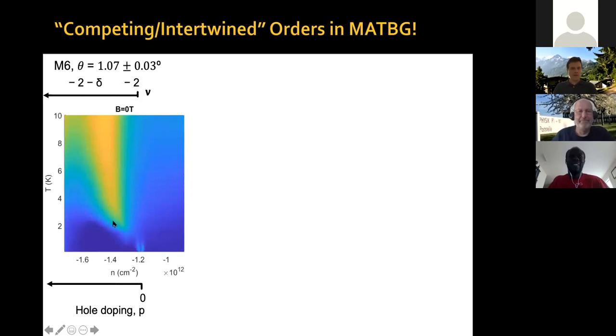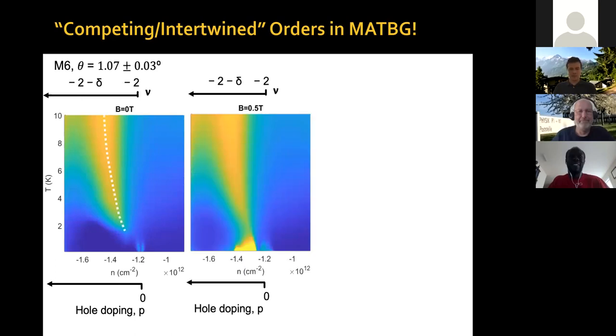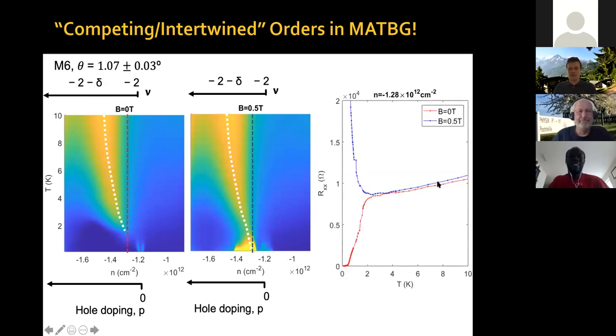So this is another example. This is sample M6, 1.07 degrees plus minus 0.03 degrees. You have, again, this high temperature feature, this banana as it's called here. The correlated insulated state at nu equals -2 is actually very, very weak. This creates a depletion in TC. If you apply a small perpendicular magnetic field, you can see that this high resistance ridge goes into an insulating state next to, but not exactly at, about 10% doping from the correlated insulated state at filling factor -2. And again, if you take a trace there, you can see that in one case you go superconducting, in the other case you go insulating when you have a finite magnetic field applied.